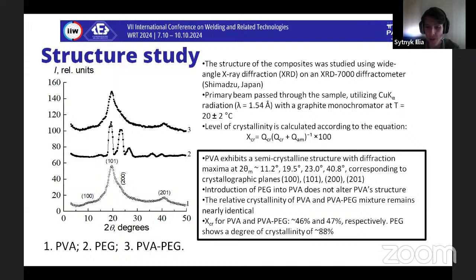Analysis of the structure of polyvinyl alcohol showed that this polymer is characterized by a semi-crystalline structure. This is confirmed by diffraction maxima at 11.2, 19.5, 23 and 40.8 degrees, which correspond to crystallographic planes with Miller indices 100, 101, 200, and 201. It was established that the introduction of polyethylene glycol into the PVA composition does not affect the structure of the PVA itself, since there is no change in the angle position and intensities of the diffraction maxima.